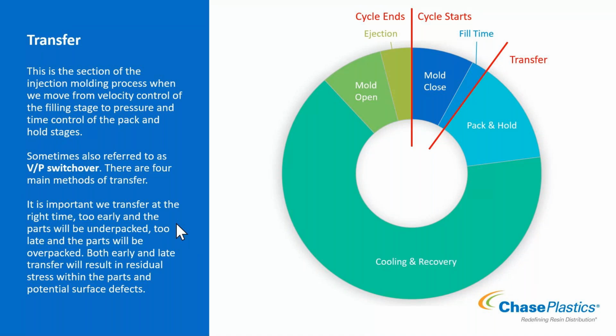On the other hand, if we transfer too late, we can flash the cavity, or we can diesel, or we can mold in a very high amount of molded in stress and residual stress, which will result in the part likely failing prematurely under load in application. So getting this position correct is extremely critical to the performance, repeatability, and quality of the molded product.